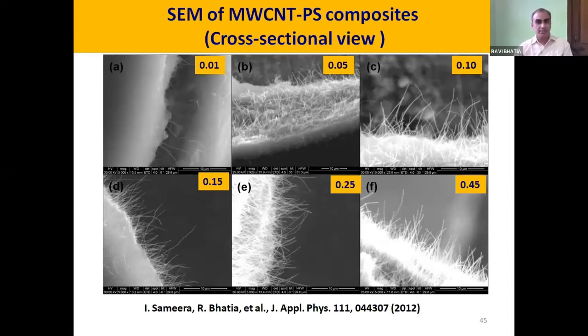The problem with CNT alone is its thermal stability is okay. There is no problem with thermal stability, but its positioning within the chamber is difficult. So we chose this polymer composite route to study field emission properties, and these are the SEMs which are showing that when you have a composite sample, you cut it with a sharp knife and vertically align it in the direction of the electric field.